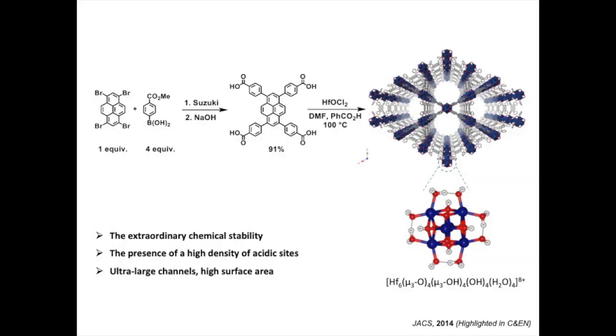And this is one of the examples of the metal organic frameworks that was prepared, and you can see that we can have large hexagonal and trigonal channels, and it has several features like a high surface area, very high stability, and the presence of a high density of the metal cluster, which in this case is hafnium. So let's have a look in depth at this material.